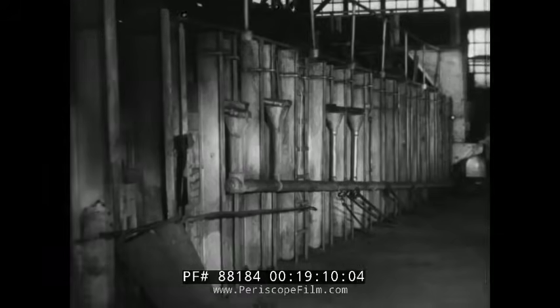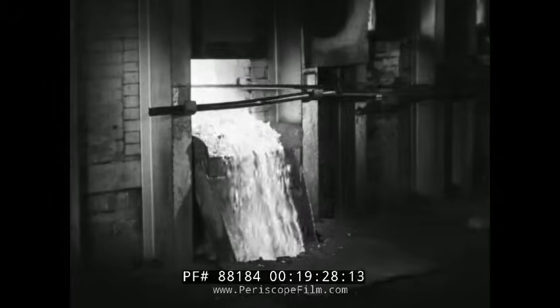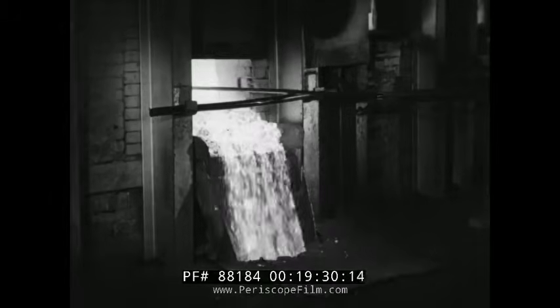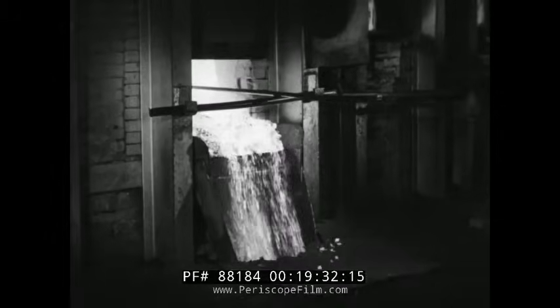A hopper at the back end of the calciner receives the charge. The matte is moved forward in these long calciner furnaces by a series of mechanical rabbles. The sulfur is removed progressively as these heavy rabbles stir and push the matte forward. The Monel oxide, now sulfur-free, is drawn into buckets.